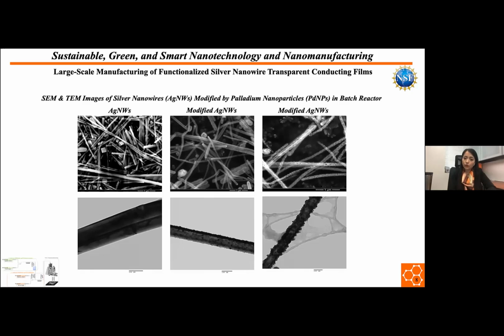by which we can see that we can deposit the palladium on the surface of silver nanowires. However, it's really important for us to have silver nanowires modified using palladium nanoparticles at just about 5% to make sure that they are stable against oxidation as well. But at the same time, we are not reducing the smoothness of the surface of silver nanowires, and we are not decreasing the conductivity of silver nanowires, which is important for us.